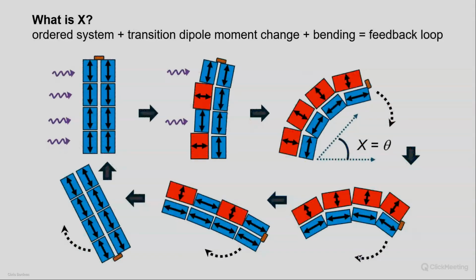And so this is just sort of an illustration to make that a little more plausible. I would start with a crystal, and it has the transition dipole moments oriented vertically, and the light comes in, and I get photochemistry, which is great. That photochemistry does 2 things. It expands one side of the crystal, and it also changes the orientation of the transition dipole moment. So now the crystal starts to deform. As it deforms, it's absorbing less light because it's bending out of the light path.